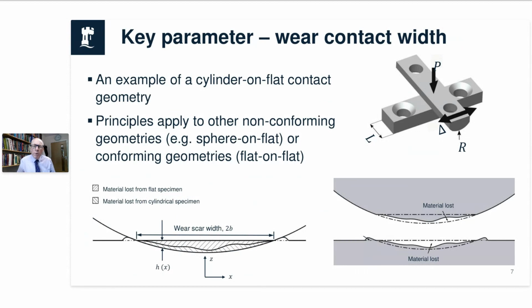The work that I'm going to present, it's one of the things that as time has gone on, you realise that actually non-conforming contacts such as ball on flat and cylinder on flat are actually much more difficult than flat on flat contacts. And it's partly because we've now come to a position where we say, actually, we think one of the key things that controls wear rate in many tests is that of the contact size, the contact width.